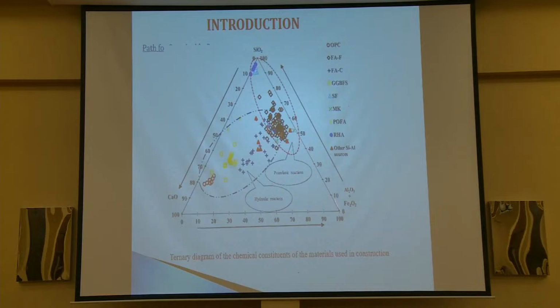And therefore, if we have a material which is rich in these 3, silica, iron, and aluminum, this means that this material has a pozzolanic reactivity. This material can be used as cementitious material if we give it an activator. We activate it with other material. And if we go to the bottom of the diagram, here we have these kind of materials that are rich in CaO, calcium oxide, and therefore these materials have the potential to be reactive with water, and they can also replace the cement. So chemically, when we classify these materials, we need to take care of these substances. These are the 4 main oxides that we need to consider.